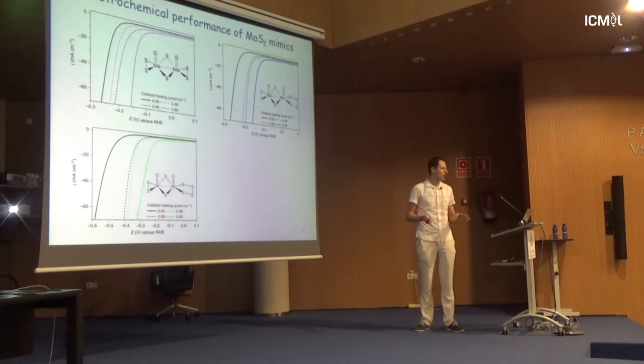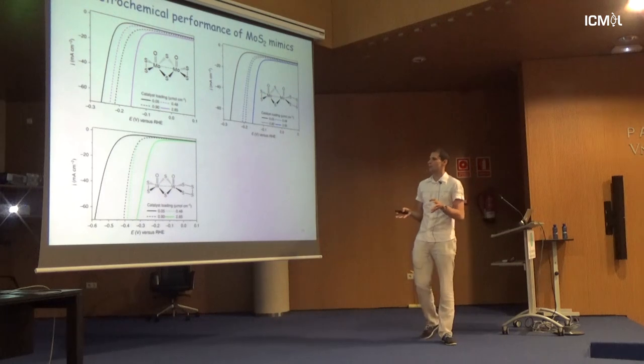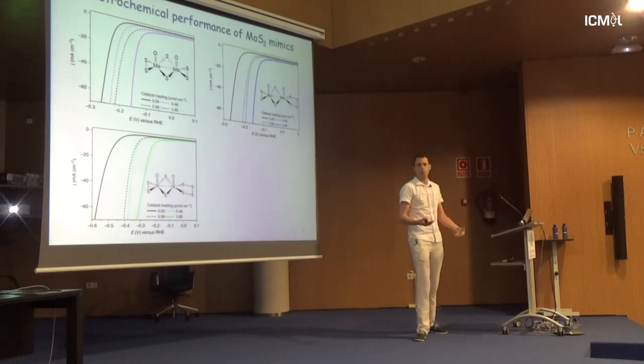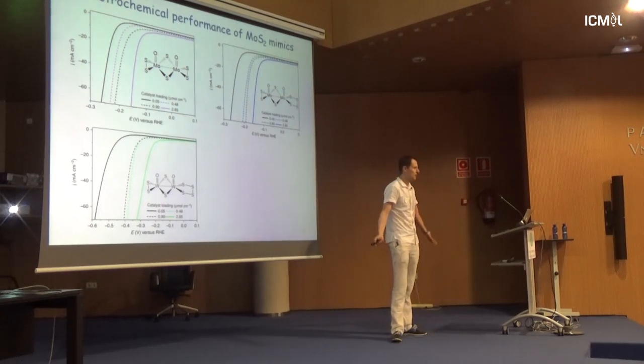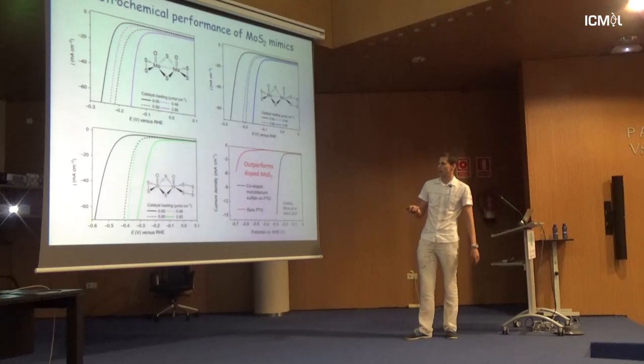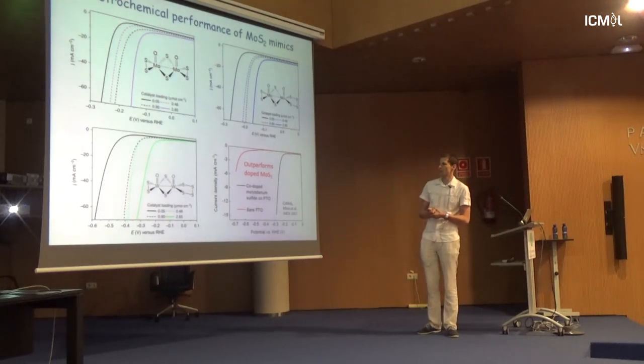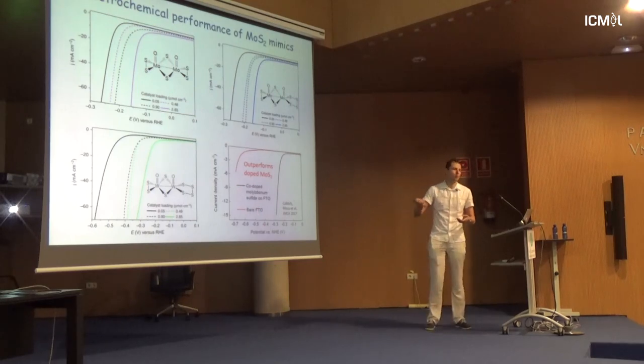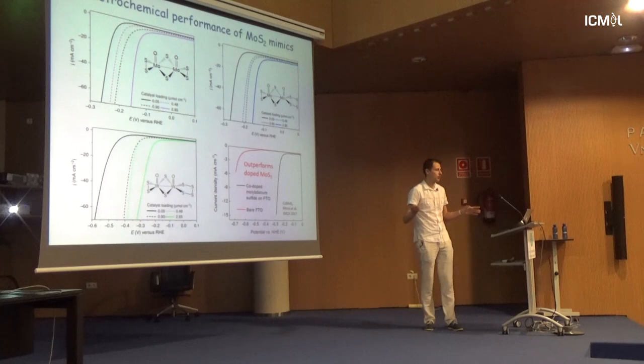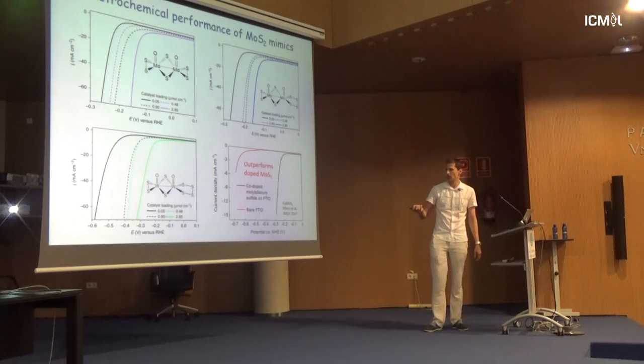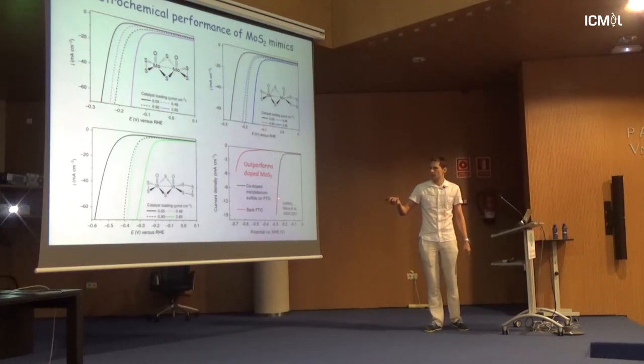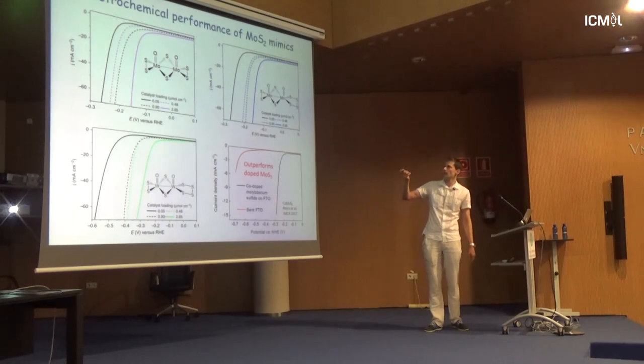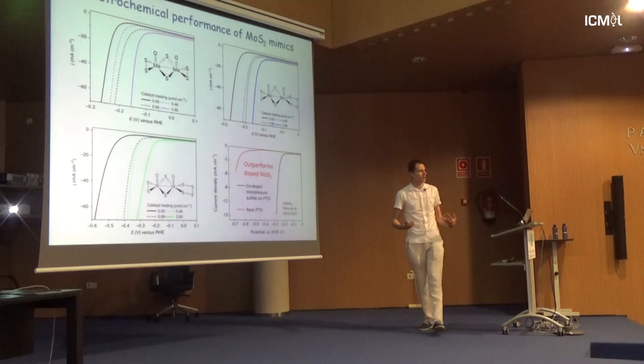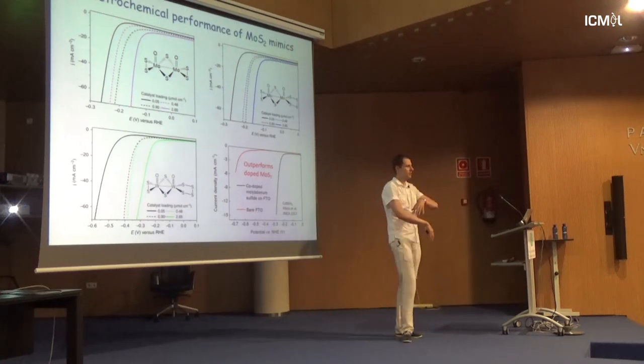However, tungsten didn't perform good at all. Molybdenum and tungsten are pretty much the same, so at that time, when we started, we blamed the tungsten. Tungsten must be rubbish, molybdenum must be very good. At 10 milliamperes per square centimeter, and this is our published data on cobalt molybdenum sulfide, they outperform the molybdenum sulfide substantially. We hardly get any current densities on molybdenum sulfide, so our overpotential at 10 milliamperes would be about 260 millivolts, while here we're talking about 110.